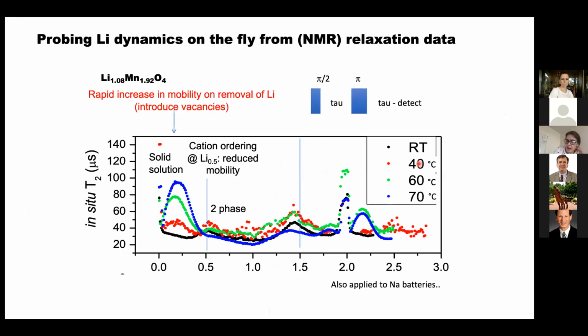And then you can start to ask questions like, can we say something about the phase transitions? This is now looking at the same material as a function of temperature, going from room temperature to 70 degrees, and going from lithium 1 to lithium 0.5 to lithium 0. In the first region, as a function of temperature, the T2 varies all over the place, which is consistent with solid solution behavior. In the second region, you have an almost constant value of T2, where the value at 0.5 stays almost the same as at lithium 0, where there isn't actually any lithium left. But that's indicative of a two-phase reaction.